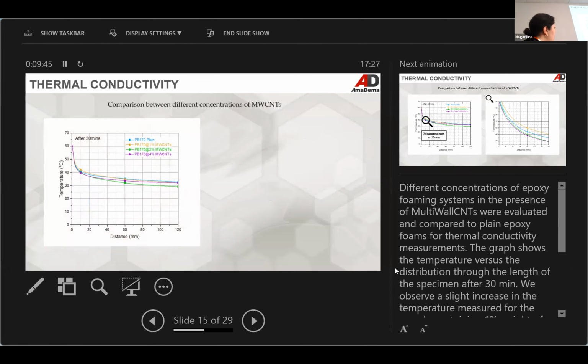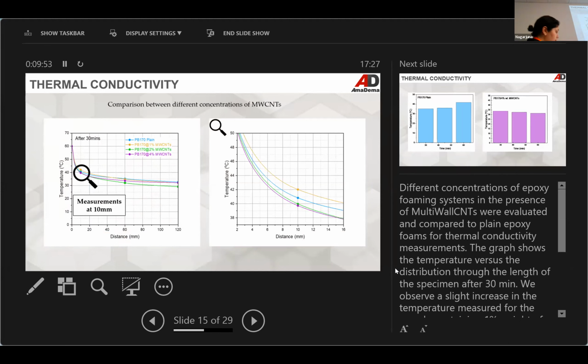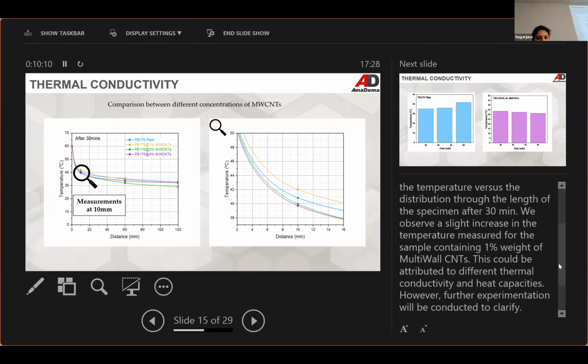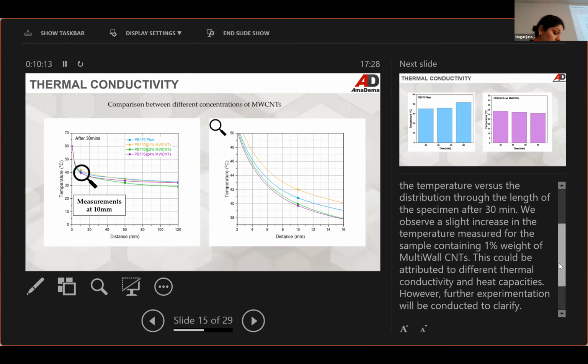Okay, so we've ended up with this type of graphs. We have temperature across a certain distance of the sample, and if we zoom in at 10 millimeters from the heating plate, we see that there is a minor increase in the case of the incorporation of 1% multi-wall CNTs. Of course, this is not conclusive yet. We really have to investigate what is happening in terms of the heat capacity of the system, and this is what we're investigating now. But indeed, we see a small increase of the temperature at a constant distance and constant time.